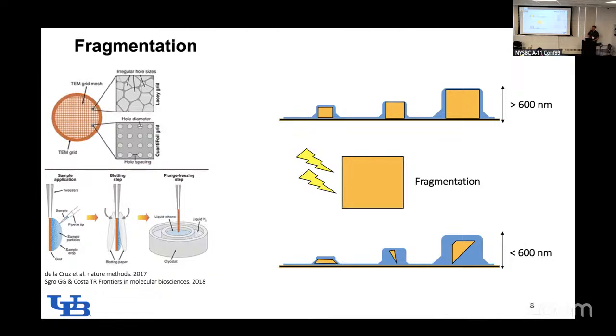One way of dealing with case 1, where I have something that's just bigger than 600 nanometers, is I can fragment these crystals. Fragmentation was shown by De La Cruz et al. in Nature Methods 2017, back when we were at Geneva. It's that guy there, ask him the questions. In Jason's paper, they took a whole bunch of samples and showed that we can just collect the crystals and put them in a little Eppendorf tube and just dip it in a bath sonicator, and the crystals fragment into little pieces. You can also grab a pipette tip and just crush them. There's a whole bunch of tools from Molecular Dimensions for poking crystals and breaking them as well. You can buy these glass beads, all kinds of stuff for fragmenting them into small parts.